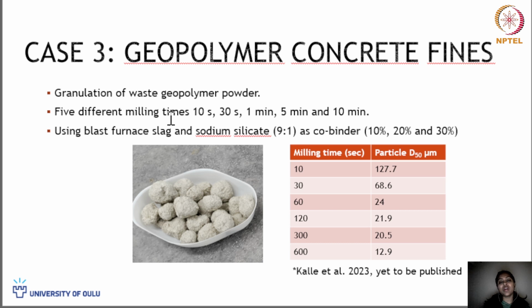Here our aim is to understand if we produce these fines in different particle size distributions, how that could affect the strength of these granules. So we milled it for different times, and we used some blast furnace slag and a very small amount of sodium silicate as the co-binder. Blast furnace slag 90% and sodium silicate 10% is used as co-binder in proportions of 10%, 20% and 30% together with the geopolymer concrete fines.